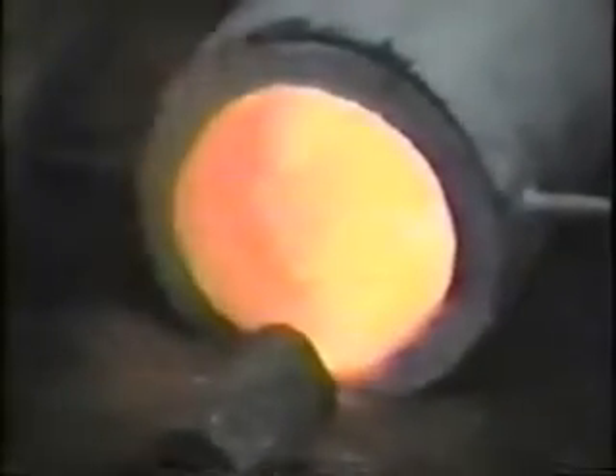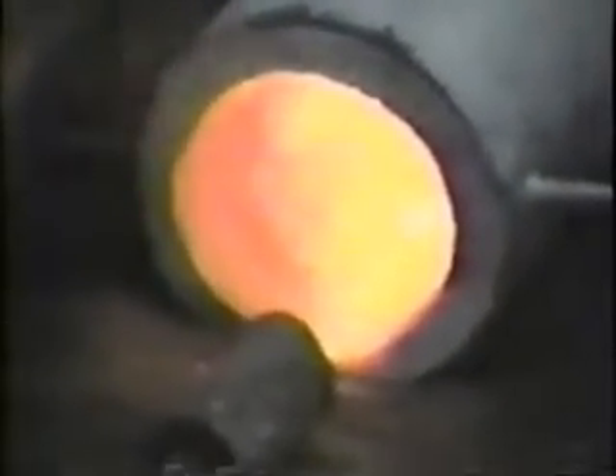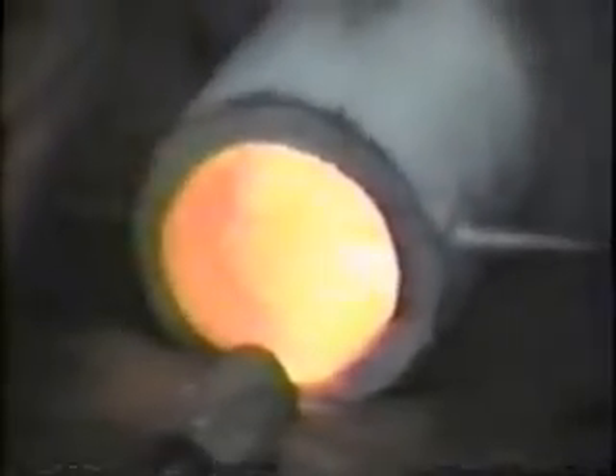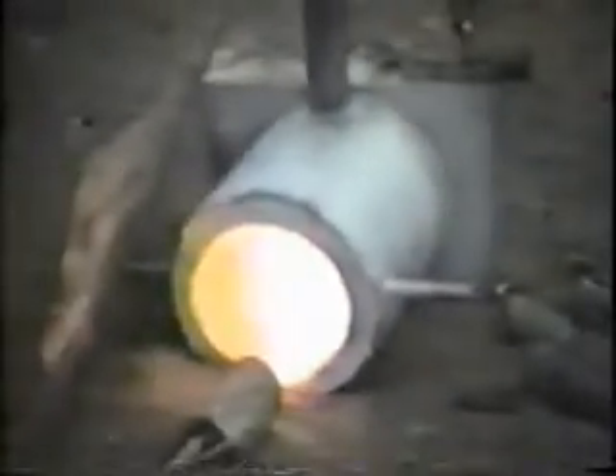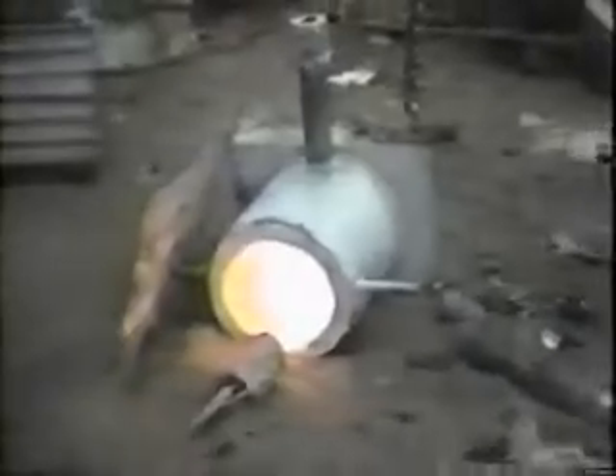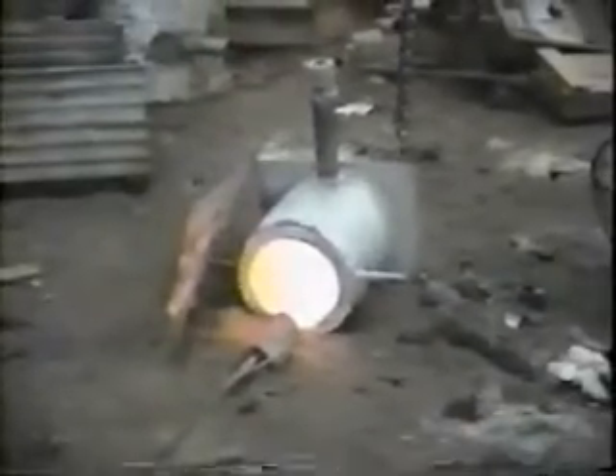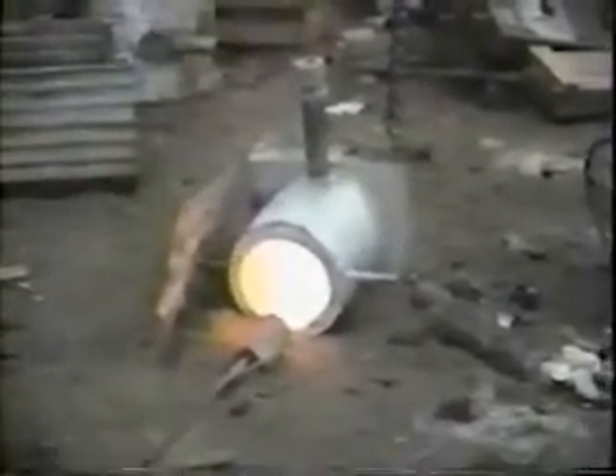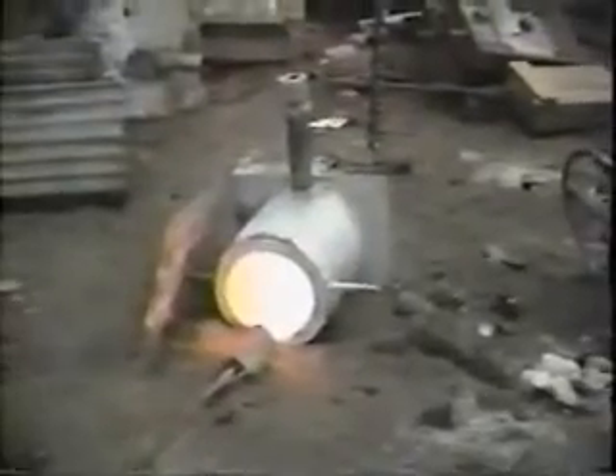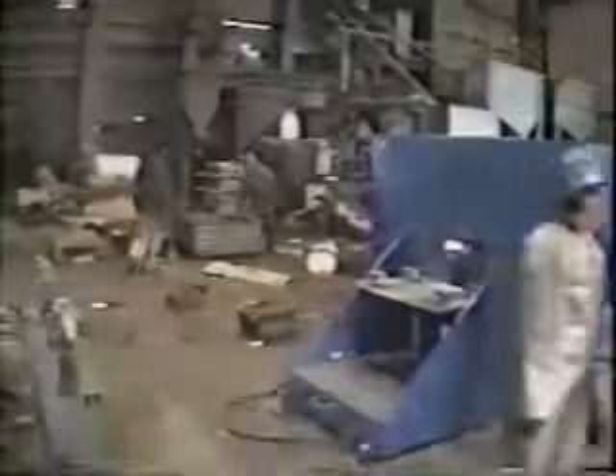While the lance is being used to coat the mold, the runner pot or funnel for pouring into the mold is being preheated by gas torch. It's preheated to a temperature of about 1600 degrees. At the same time, this pouring pot is being heated. Also, the transfer ladle is being heated to appropriate temperatures to avoid temperature loss.